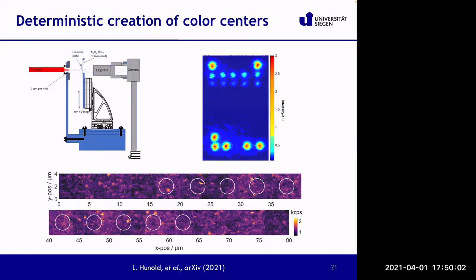And so the question was how to go to single emitters, and this took a lot of time because there are secondary ions that are scattered by the pinhole and so on and so forth. But eventually we got to the situation that you see in the bottom panel, in which you have these circles, and in these circles, sometimes we get a single emitter. So you cannot get a deterministic creation because the activation of the color center is still a stochastic process, but you can get a good probability of placing a single photon source in the desired position.